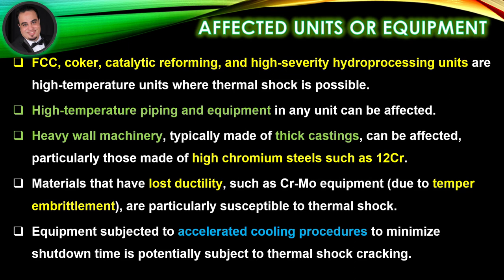Materials that have lost ductility, such as chromium molybdenum equipment due to temper embrittlement, are particularly susceptible to thermal shock. Equipment subjected to accelerated cooling procedures to minimize shutdown time is also potentially subject to thermal shock cracking.